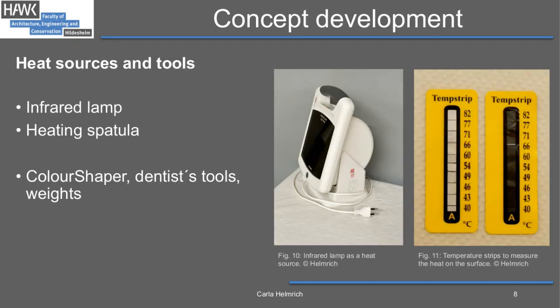The use of an infrared lamp, this one down here, in combination with a heating spatula proved to be very suitable. The softening temperature of the paint was determined empirically with the help of temperature measuring strips, these ones. They change color when the temperature is reached. They can be placed right on the surface, so they actually measure the temperature of the surface and not of the heat source. A flexibilization of the brittle paint could be determined at temperatures between 75 and 80 degrees.